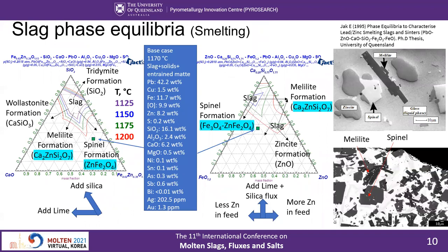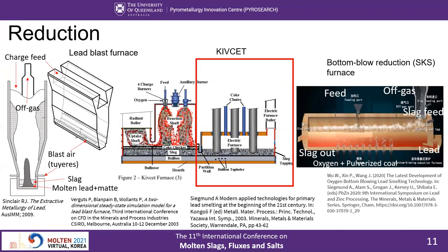The bulk composition of slag in the base case is projected onto two different diagrams. The left diagram is good for analyzing the effect of silica and lime fluxes. The slag at 1170°C is below liquidus. It must be mentioned that fluxing during the smelting stage is often targeted to provide fully liquid slag at the next reduction stage. The reduction stage can be less tolerant to the presence of solids. For instance, in the blast furnace, the goal is to settle the slag and metal layers in the hearth, so agitation is avoided. The right diagram is suitable to understand the effect of the zinc-to-iron ratio in the feed on the liquidus of slag.